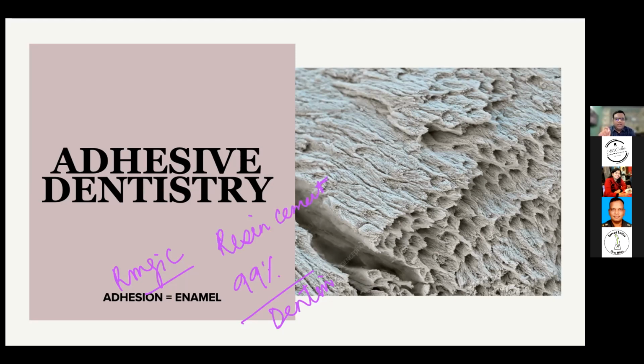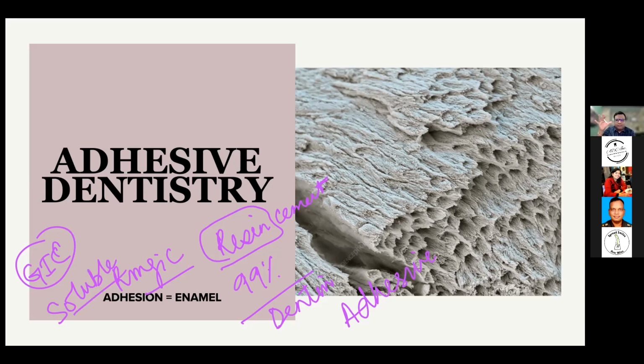Trust me, guys, resin doesn't bond to dentine unless you make it bond to dentine. You will need to follow the adhesive protocol. The only thing that can bond as a true bond to dentine in dentistry is this material called GIC. It is still the best material if you are looking to bond to dentine. The only problem with GIC is that it is soluble. So GICs will fail from the outside, from around, and then they come inside, because the last bond to fail on a GIC would be a dentine bond.